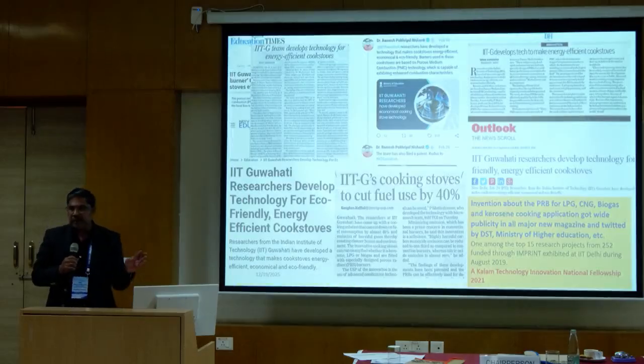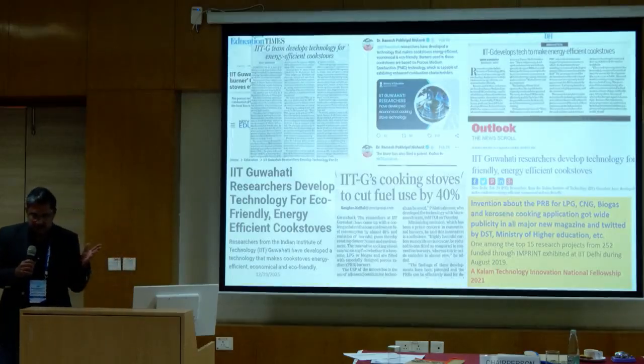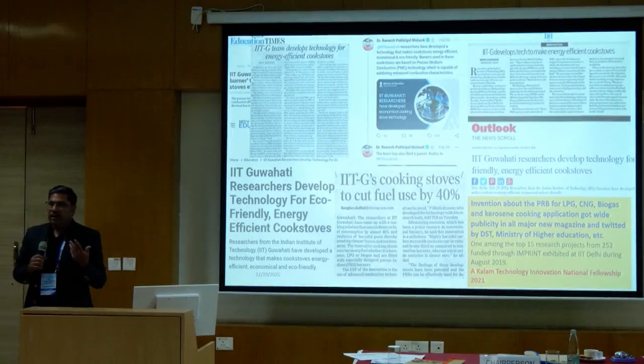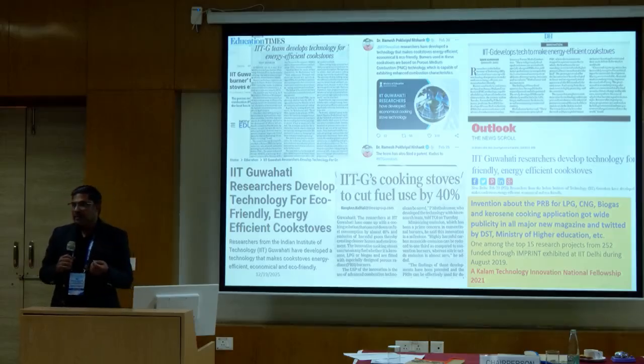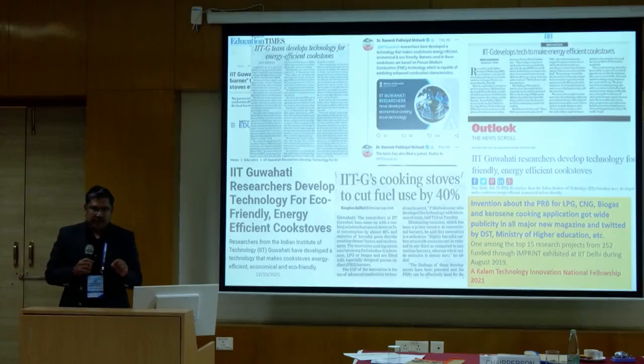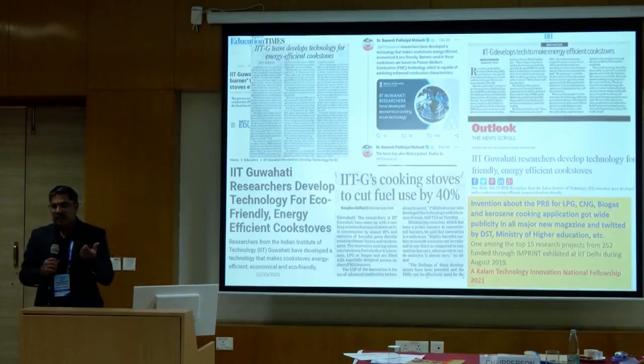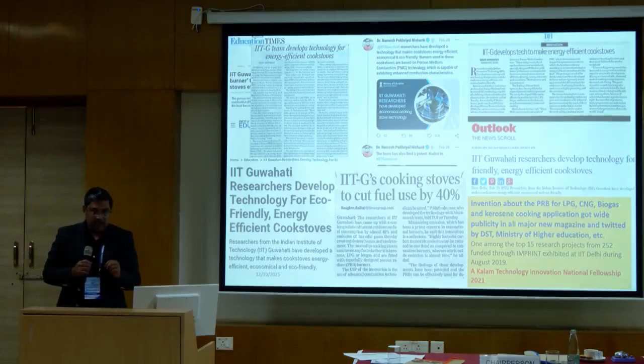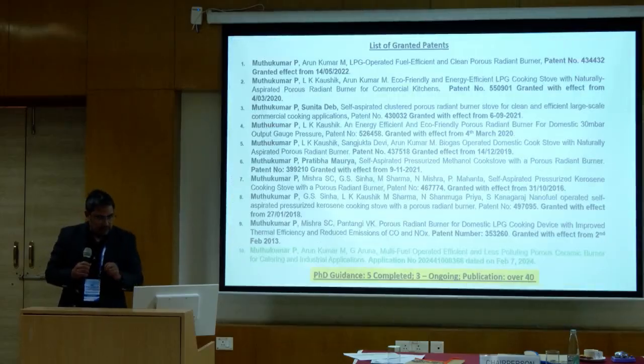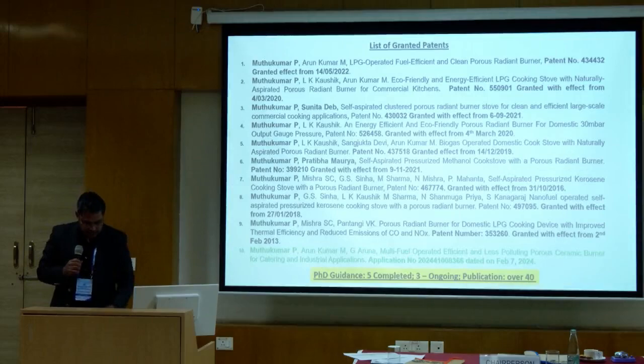Now coming to the burner, designing such burners is not so easy since it's a ceramic. If you don't do it properly, you will end up with flashback and fire blow-up. So particularly the porosity and the thickness need to be carefully designed. We have done extensive thermal modeling, and with its help the porosity and diameter, even the mixing tube and the nozzle, are finalized. Nearly 7 PhD students have worked on this, 4 have already graduated and 3 are currently working. This has received several recognitions. We have about 10 granted patents and a few are in the pipeline.